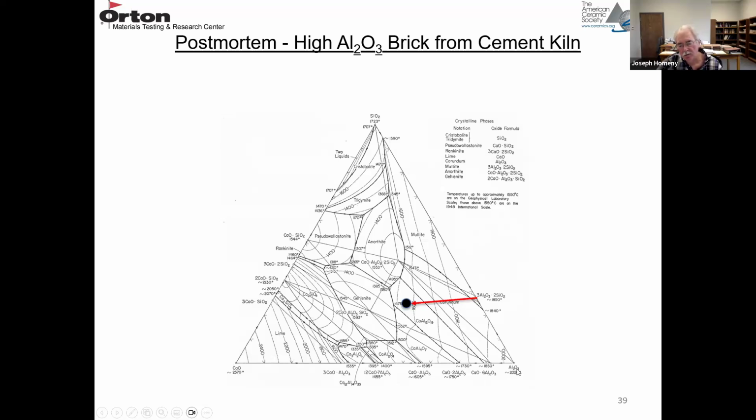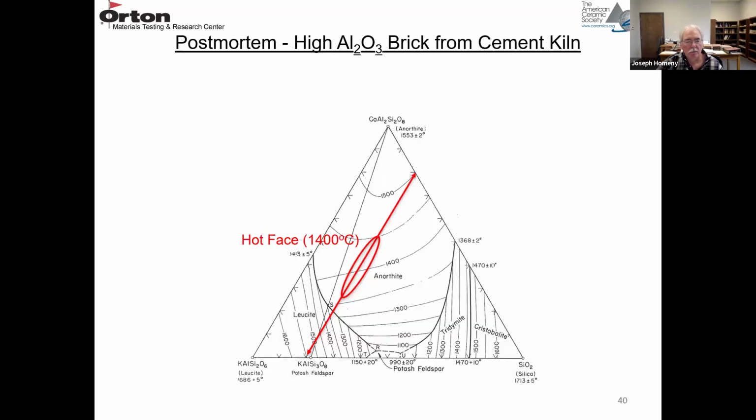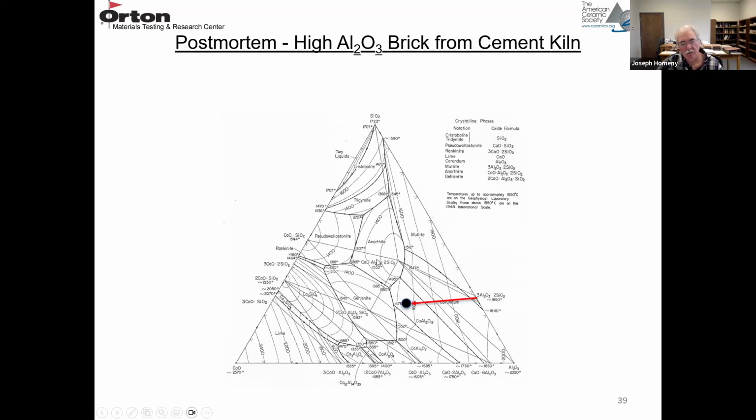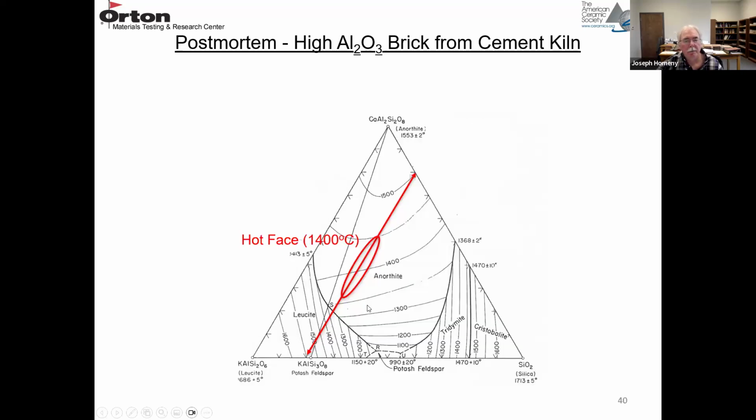And then I did the same thing with alumina, silica, and lime. I started at mullite, and this composition is shifting in this direction to this other low melting phase field, gehlenite. So I found the phase diagram for silica and anorthite, which is next to gehlenite here, same components, and then leucite, and put on where the composition is falling. It's falling in this region here.